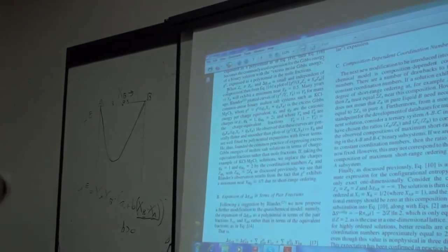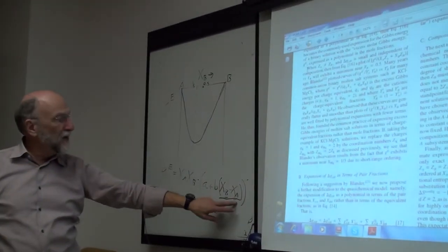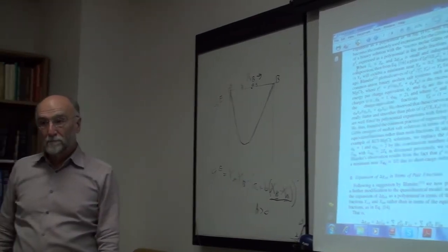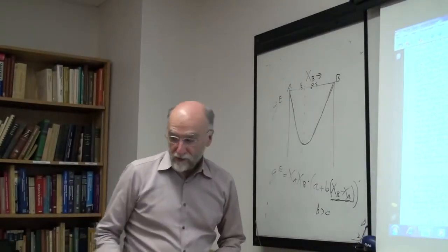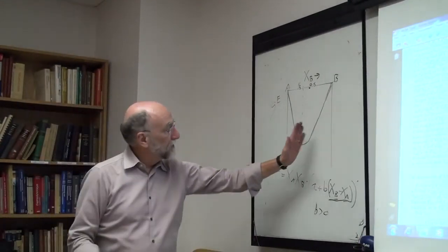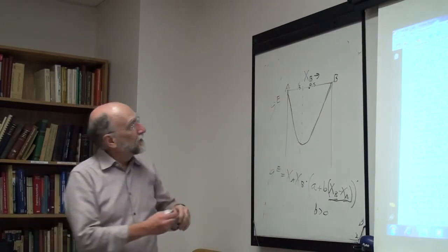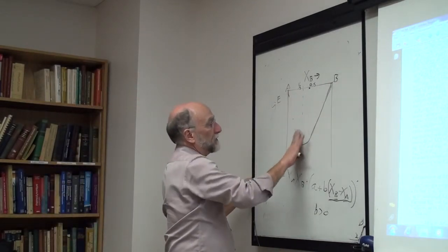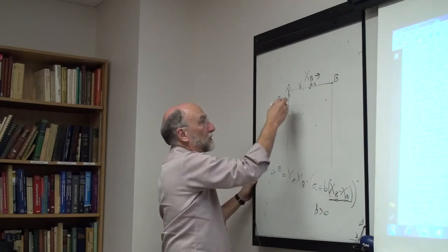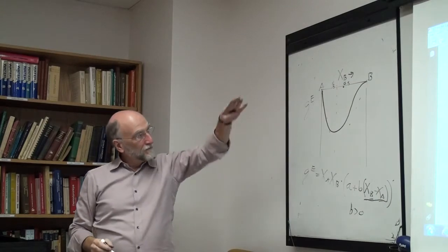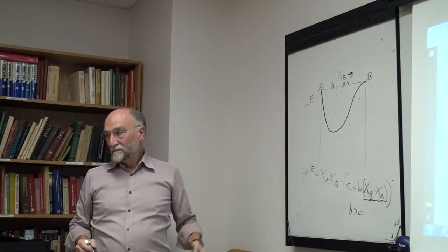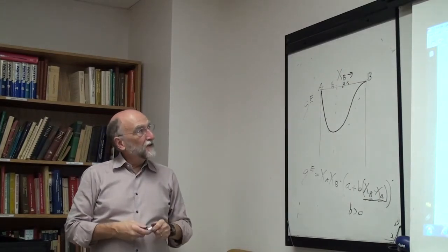The first term is a parabola. The second term flips around like this. It's negative on the A side and positive on the B side. So that is going to shift your peak over to the left, but it's going to change the shape. The shape is not going to be round, but it will be more positive here, and we'll kind of look around like that.